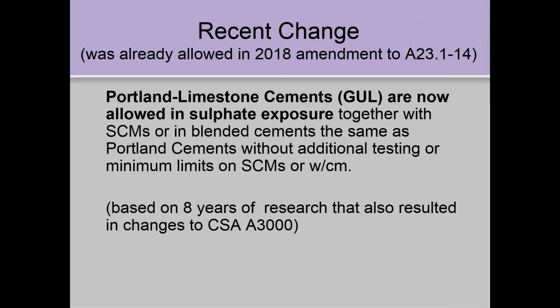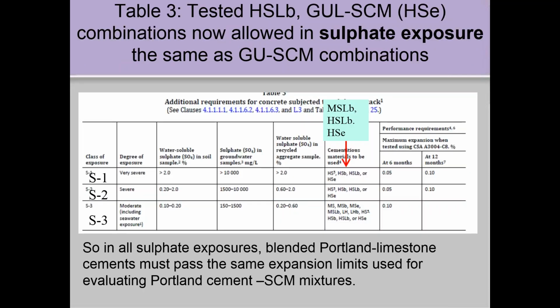Okay, well, this change was already in an amendment that came out last year in the A23, that Portland limestone cements, those cements that have up to 15% interground limestone, are now allowed in sulfate exposures. Before, we had some special requirements for testing them if they're going to be placed in sulfate exposures. But based on extensive research that I was involved in, and Mike Thomas and others were involved in, we've now removed all those requirements. And so now you just test it the way you would with any other cement. And there's no special limits on the concrete.